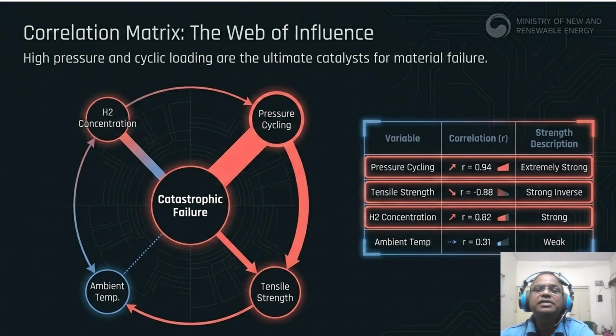Conversely, tensile strength has a strong inverse correlation, R = 0.88, meaning as strength goes up, the safety margin goes down. Hydrogen concentration is also a strong driver at R = 0.82. Interestingly, ambient temperature is a weak factor at only 0.31. So the operational takeaway is that your biggest enemy is not the weather or even the pressure itself. It's the change in pressure.